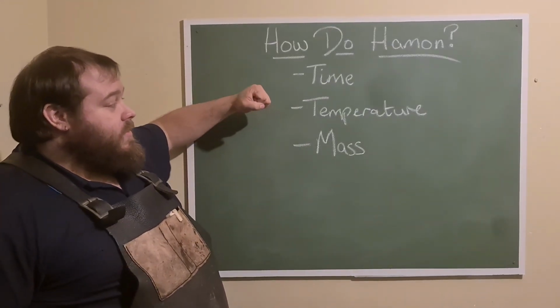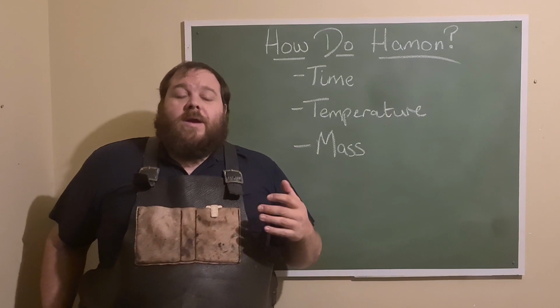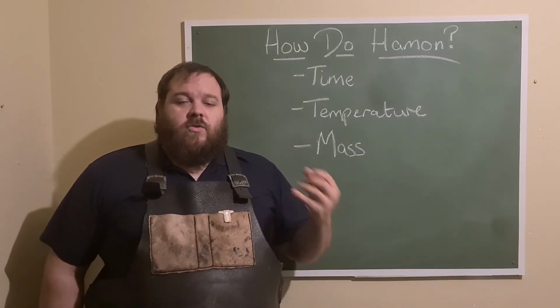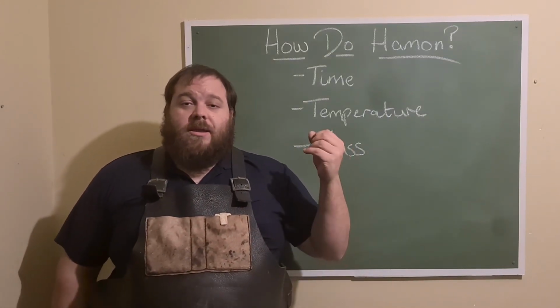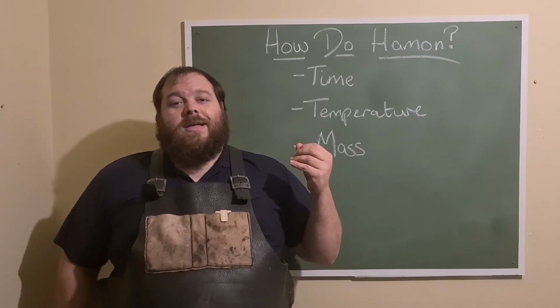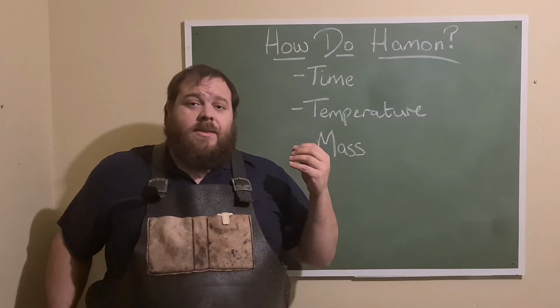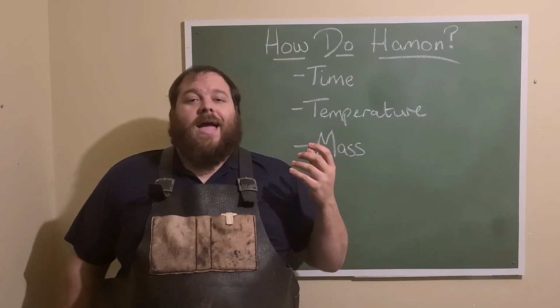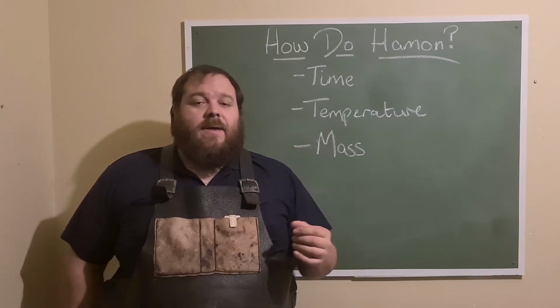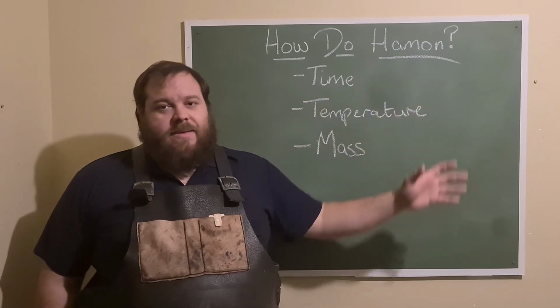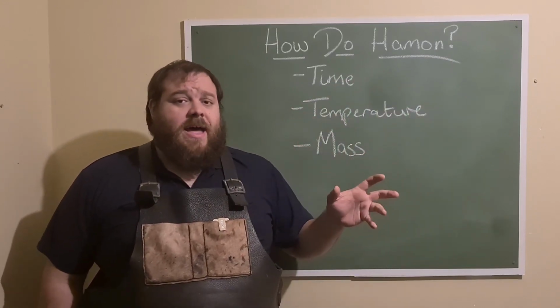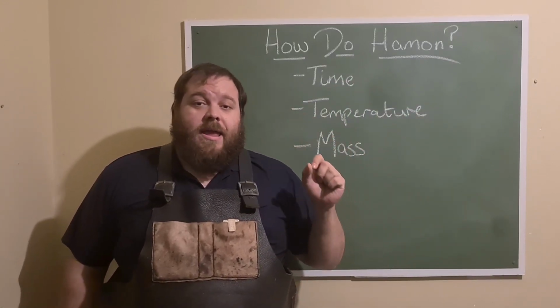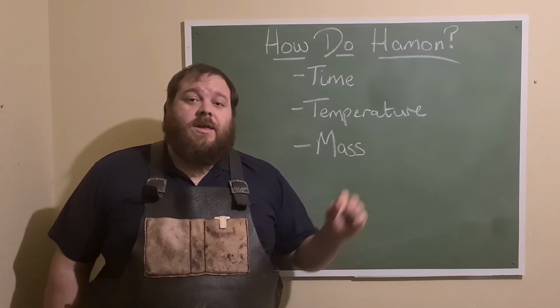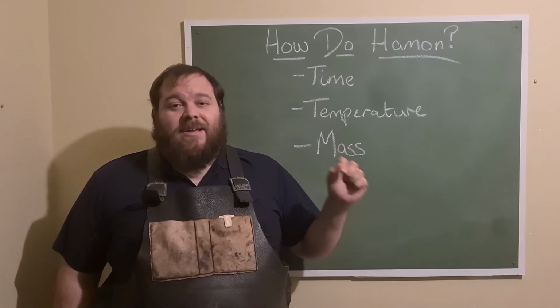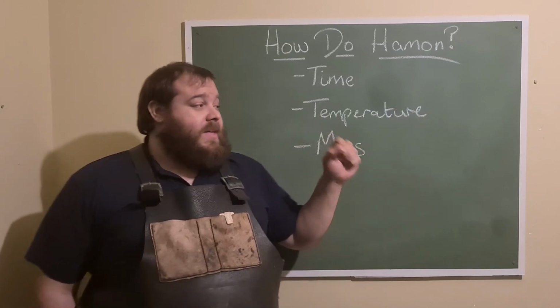Temperature is also really important. We know from heat treatment that getting to critical temperature, staying at critical temperature, and then quenching from critical temperature is the most important thing. But in the case of high carbon and low alloy steels, the temperature becomes vastly more important. The reason for that is that grain growth exponentially increases for every degree you go above critical and every second you stay above critical. So therefore, you want to get to critical and then cool it quickly.